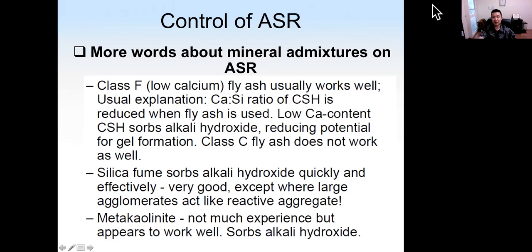All right, more details about mineral admixtures on ASR. This is about different types of mineral admixtures. Okay, so class F fly ash. Class F fly ash usually works very well, and here is the reason. The calcium to silica ratio of CSH is lower when class F fly ash is used. Okay, and low calcium content CSH will absorb alkali hydroxide. So that will reduce alkali in the pore solution, so reduce the potential gel formation. Class C fly ash does not work as well because the CSH cannot absorb alkali hydroxide as effectively. So this is very detailed information.